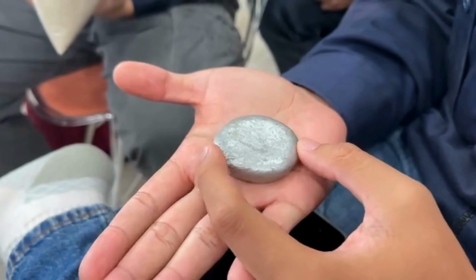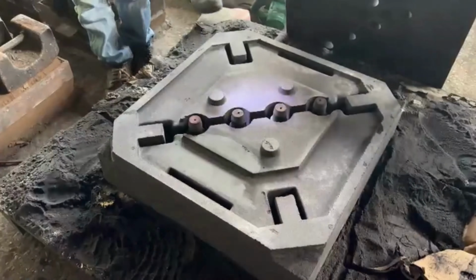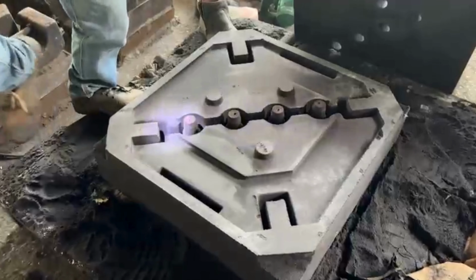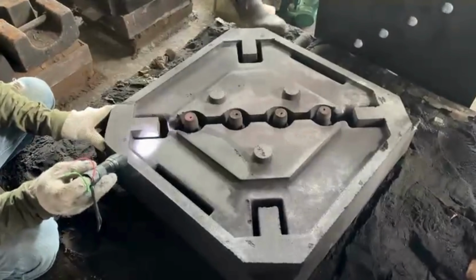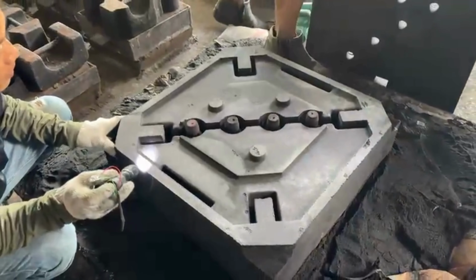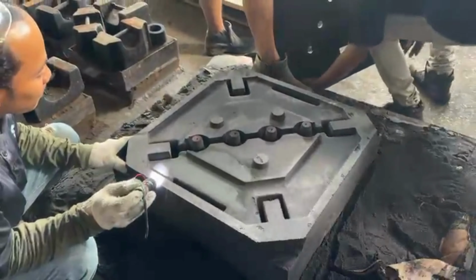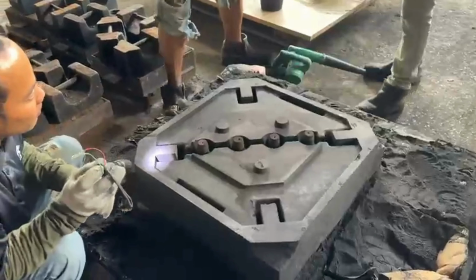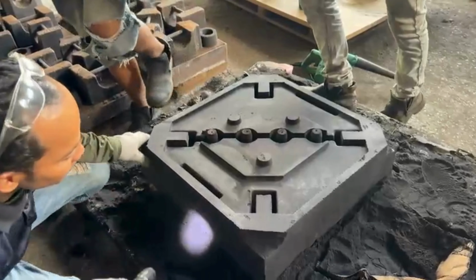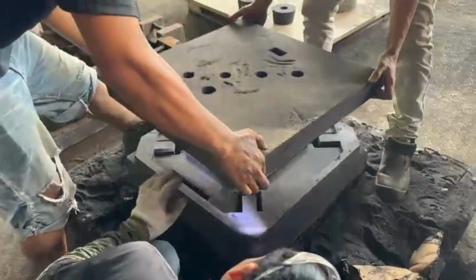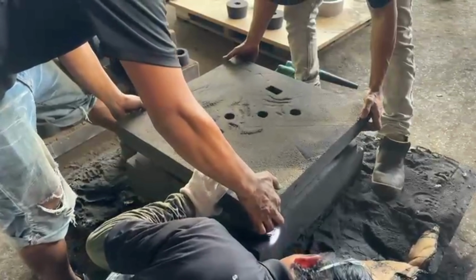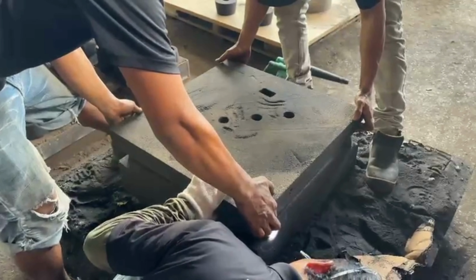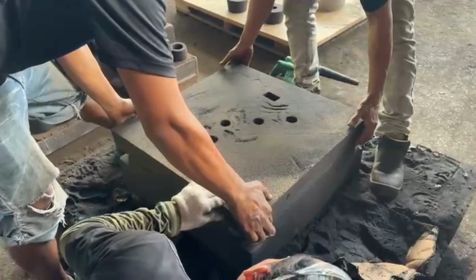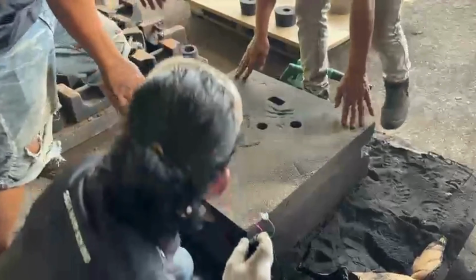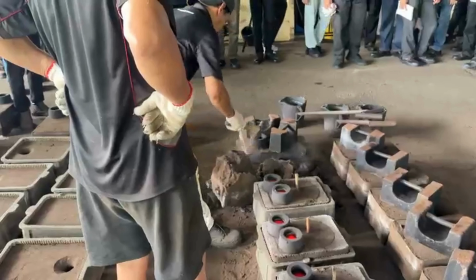When we observed the casting after the shakeout process, we noticed a major defect called blowholes, or gas porosity. These are smooth, round holes that can appear on the surface or inside the casting. This is a serious defect because it weakens the casting by reducing the amount of solid metal that can carry the load. As a result, the part becomes less durable and may fail the quality inspection.